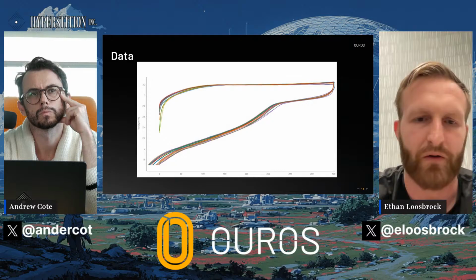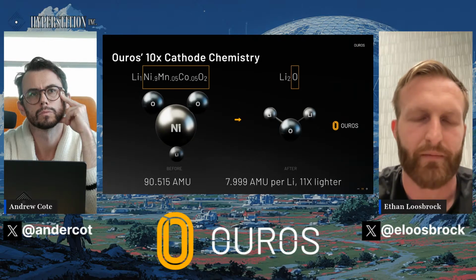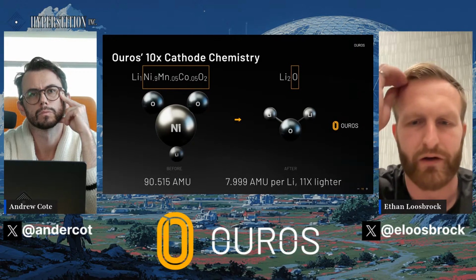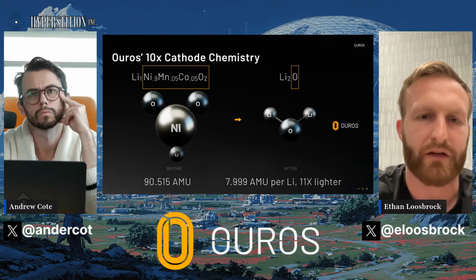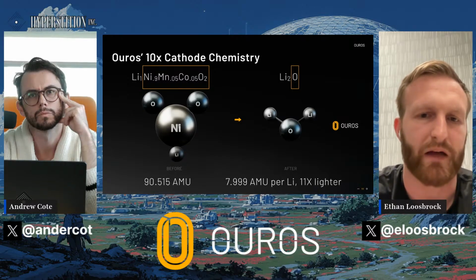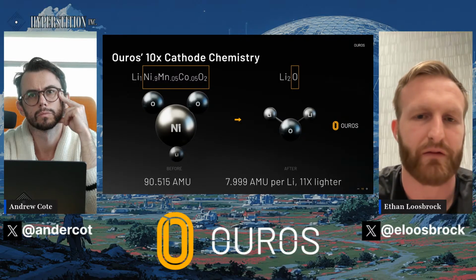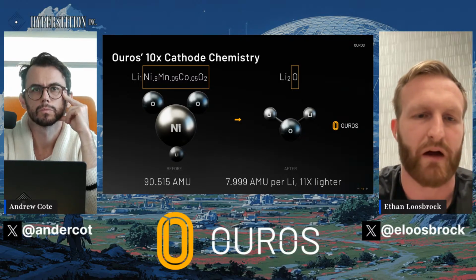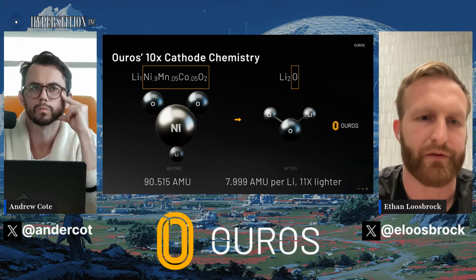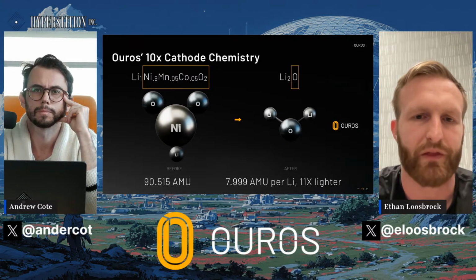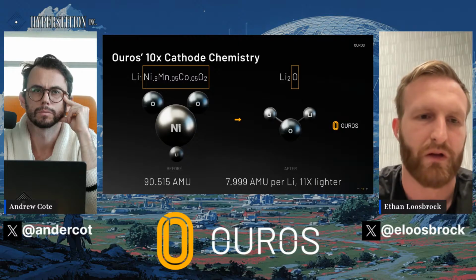So the trick with our chemistry is we start with lithium oxide, and there are two other lithium oxide compounds that you can cycle to. As you pull lithium off, there are intermediate compounds before you reach oxygen gas. So you have lithium peroxide, which is lithium 1, oxygen 1. And then there's lithium superoxide, which is lithium 1, oxygen 2. So the structure changes a little bit to accommodate that.